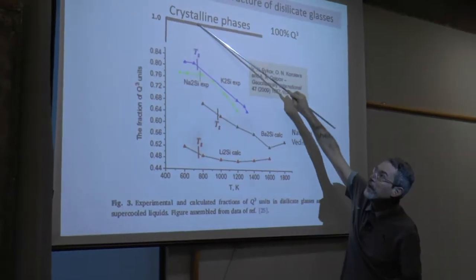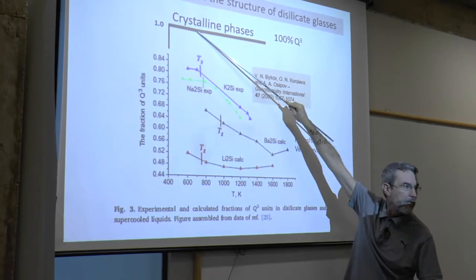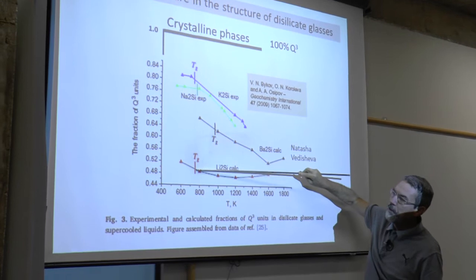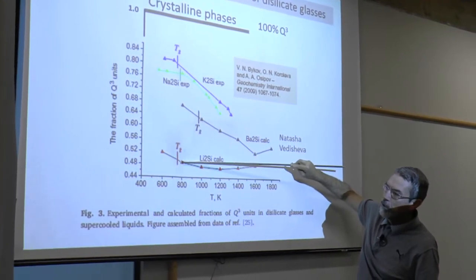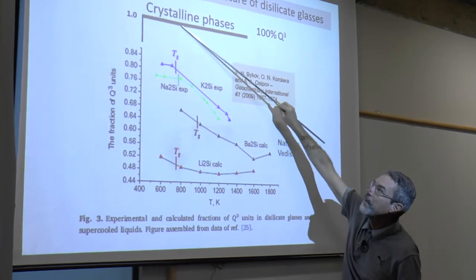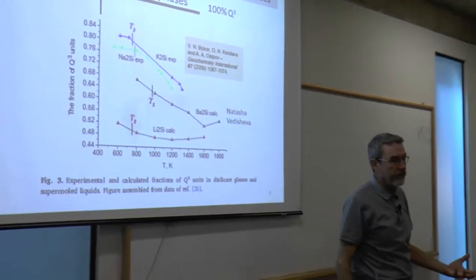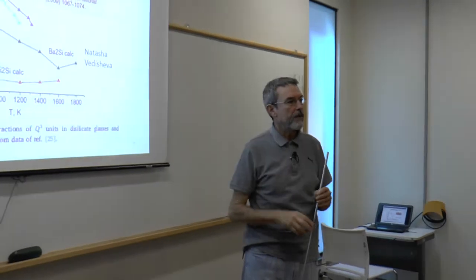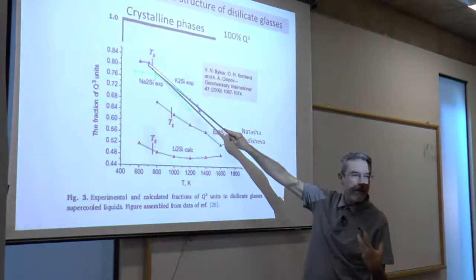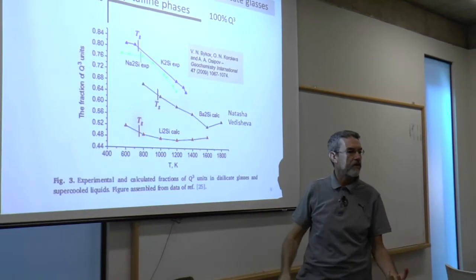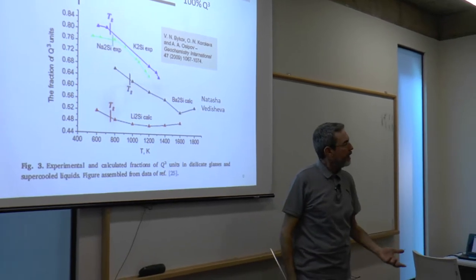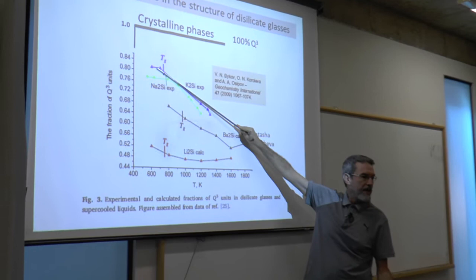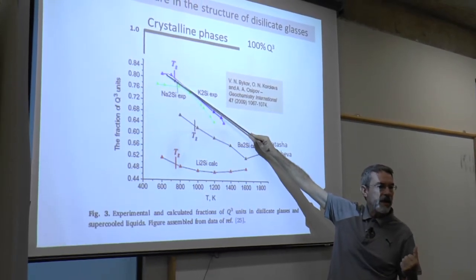In a crystallization, if you're looking at the structure of the material during crystallization, it would move from here to here. The structure of the crystal phase is 100%. If we are looking at this material here, we would move from the supercooled liquid with 50% Q3 to the crystalline phase with 100% Q3. This is the kind of structural change that happens when we crystallize, when we solidify permanently the material. So this is not a permanent solidification, it's just a freezing in of the structure, a temporary phenomenon. And then if we wait for some time, as we had seen in the previous class, the glass will relax.